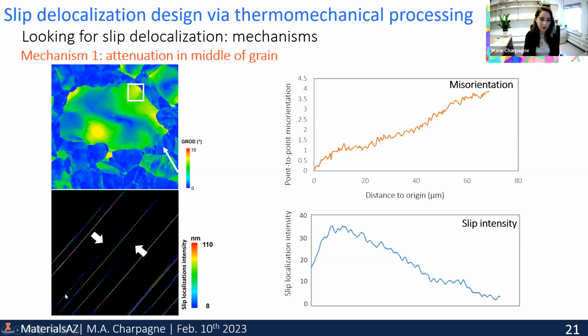And looking at the corresponding DIC map, we see that some slip bands, as we enter this region of lattice rotation, just disappear in intensity. So they decrease in intensity until they disappear. And we can plot along a similar profile on our correlated data set, point-to-point misorientation. So this is our signature of lattice rotation as a function of the slip intensity. And we see clearly that the slip intensity decreases as we go towards this region that's misoriented. So that's the first mechanism, which is good at making slip bands of lower intensity.